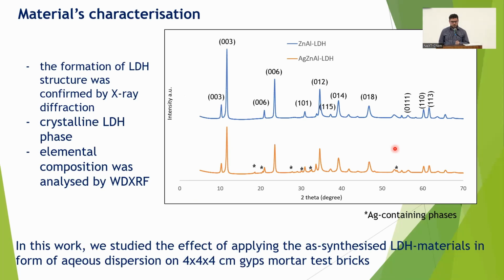We synthesized the material via a simple co-precipitation technique at low supersaturation and constant pH. We confirmed the formation of the layered double hydroxide structure by XRD. In the XRD, we can observe the specific diffraction lines of a layered double hydroxide structure. The diffraction lines are characteristic of zinc aluminum layered double hydroxide with carbonate as the anion. We also observed a little bit of impurities, which consist of wurtzite, zinc oxide.